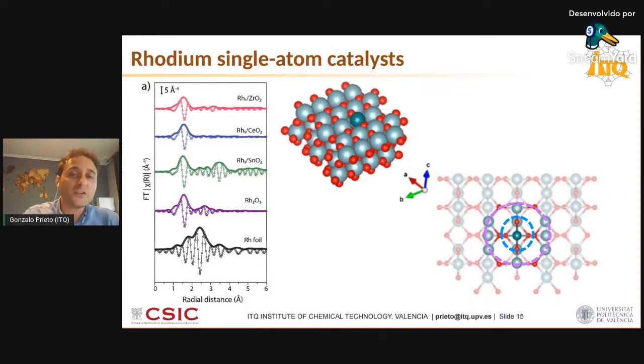This is typically, I have to say, insufficient to claim single atom dispersion. And in some cases, it's even impossible. Look at, for instance, the X-ray spectra, the green one for the rhodium single atom on tin oxide. There are very clear modulus signals at radial distances far beyond the rhodium-oxygen first coordination shell. And this is due to the fact that, due to the crystalline symmetry of the oxides, in some cases we are going to have constructive interference effects at second shell and farther distance coordination shells, which are not associated to rhodium atoms, but may be associated to cationic centers on the support itself. And it is not trivial to tell whether or not there is information about rhodium oxo-aggregates or even rhodium-to-rhodium coordination in nanoclusters.